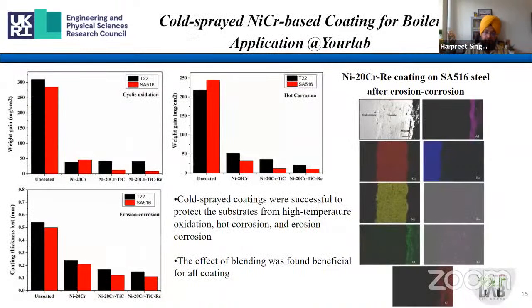Now, this is some work which we have done. I just wanted to show, especially on cold spray coatings. We have done this work, in fact, in 2009, in collaboration with ASB Industries USA. At that time, we were working on these nickel chromium coatings, nickel 20 chromium coatings, and we wanted to enhance the performance of these coatings, because we were designing them for boiler applications, where there's a lot of erosion also taking place due to hard fly ash particles and so on. So there we wanted to enhance the properties of this nickel chromium, and we used some titanium carbide kind of reinforcements. And also we wanted to see the effect of rare earth elements, and depending on the availability we could find rhenium, basically to peg the layers.